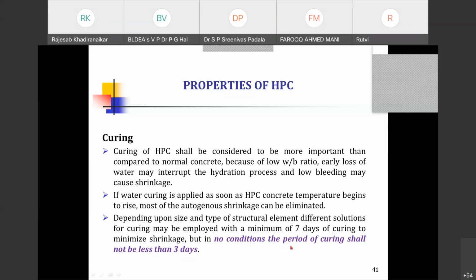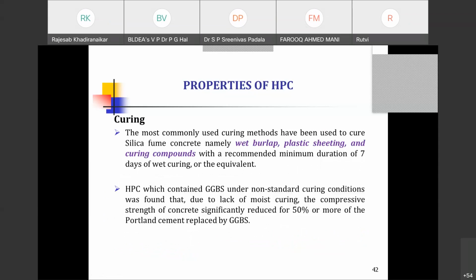Say you want to apply a curing compound in the initial period; normally they go for moist curing, and then after that they resort to other curing. But there should be sufficient curing. The most commonly used method to cure high performance concrete is with wet burlap. Initial rapid loss of moisture will be there when you use silica fume particularly. So you can use wet burlap or plastic sheeting, and then curing compounds recommended with wet curing. HPC containing GGBS under non-standard curing conditions was found to lose up to 50% of its compressive strength due to lack of moist curing.